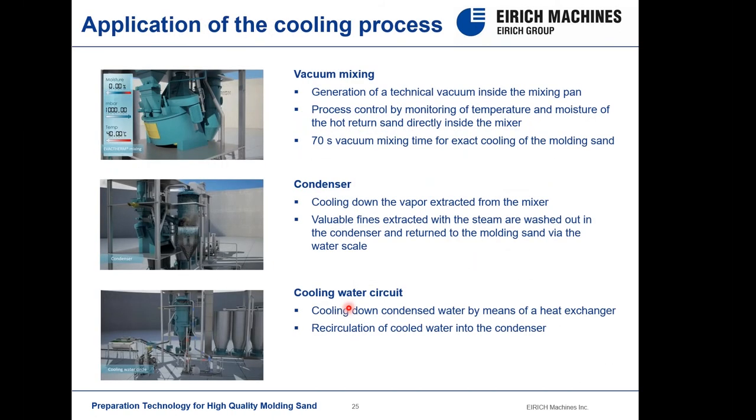So what do we do? Well, first of all, we are going to fill the mixer as you saw in the video. And then the process control is going to take the measurements as you saw, and it's going to add water into the mixing. After that, once we have that water added and mixed, as you saw in the first video, we're going to use a 70 seconds vacuum mixing time in order to take away that excess of water and temperature from the sand